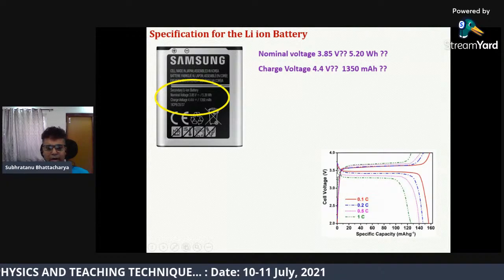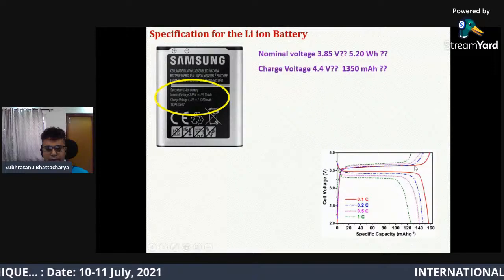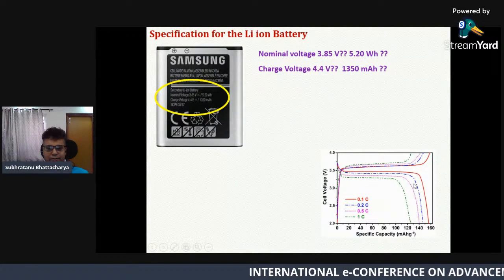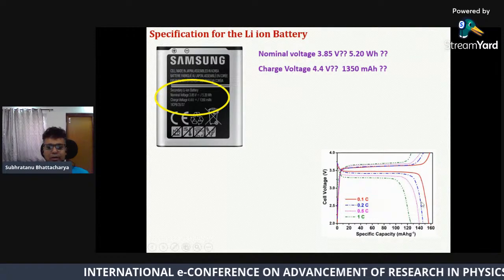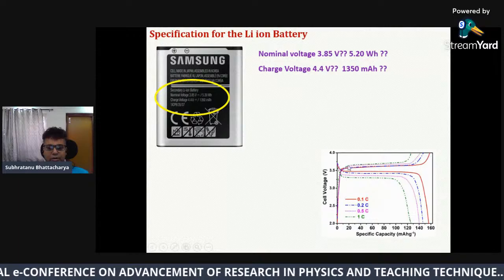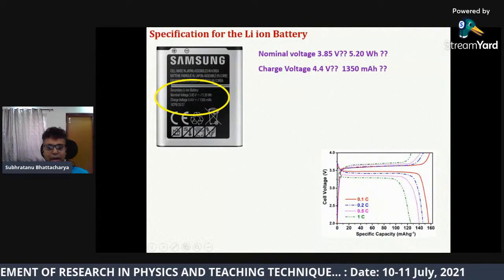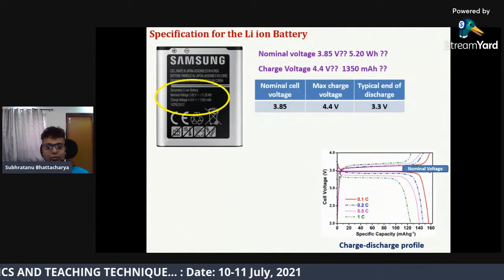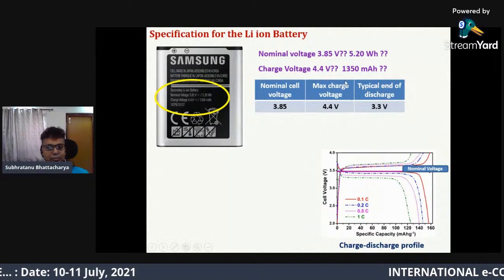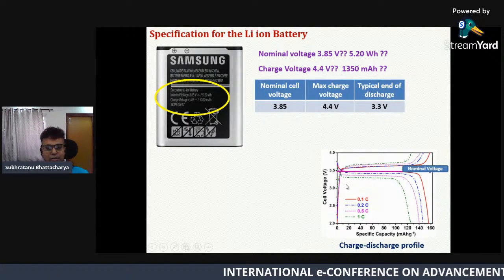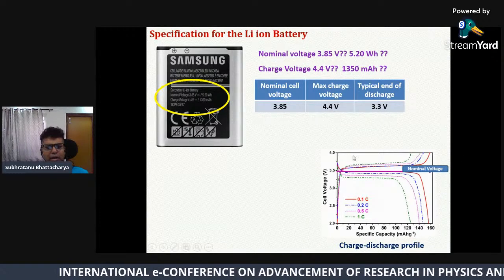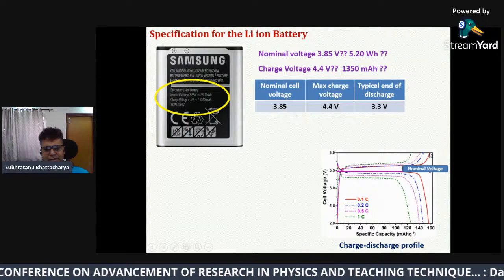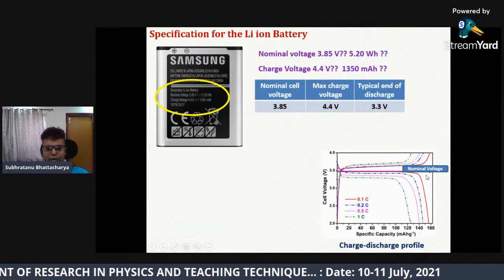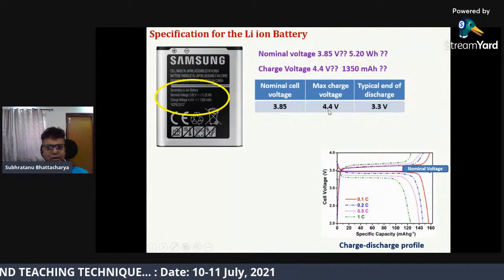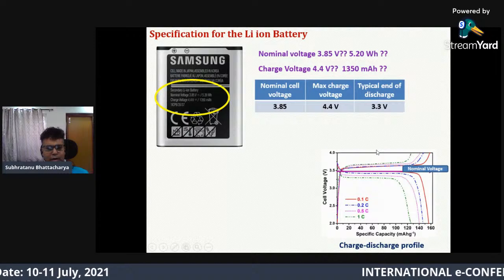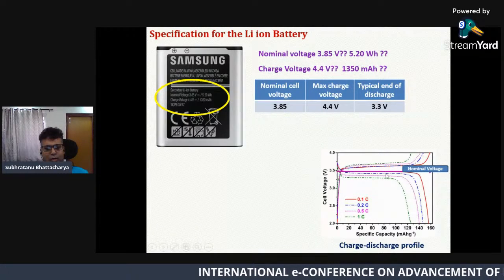Anyway, what I want to say is that you can see there is a plateau in this region. That is the most important region in a battery. In this plateau region, the battery actually works, because it will not work here and cannot work here. This plateau region is determined by the nominal voltage, that is the voltage between the maximum charge voltage and typical end of discharge voltage. This is around 3.3 volt and this is around 4.4 volt for this battery. For my battery, the nominal voltage is 4.4 plus 3.3 by 2, which is 3.85. This is the nominal cell voltage, where the plateau region occurs.